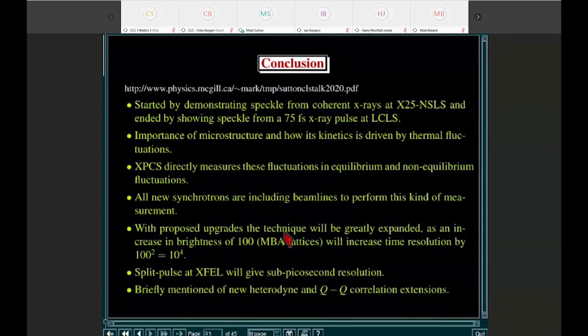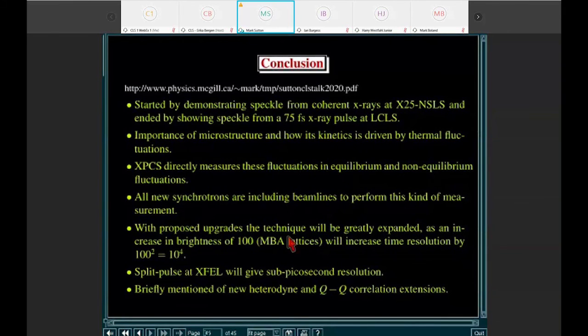And so that actually gets to the point, which we sort of emphasized a little bit with the VIPIC detector, that we're going to have to synchronize the detectors to the pulse structure of the synchrotron, and we'll be able to actually get information even between pulses by doing these pump probe and average type things. And we should be able to get the sub-picosecond, 10 to 100 femtosecond resolution even using the XFELs with these very short pulse lengths. And we're just beginning to take full advantage of sort of in between.